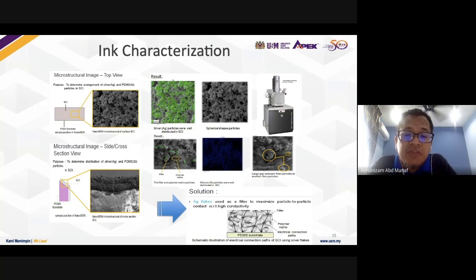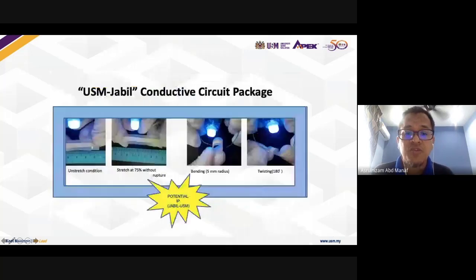So if we can reduce the gap, you can improve the conductivity. At that time, they did some mixing to reduce the gap. They changed from silver nanoparticles to silver flake, and that can minimize the particle-to-particle contact. This was the development of a stretchable conductive ink on a polymer.